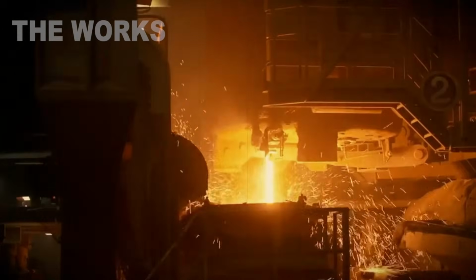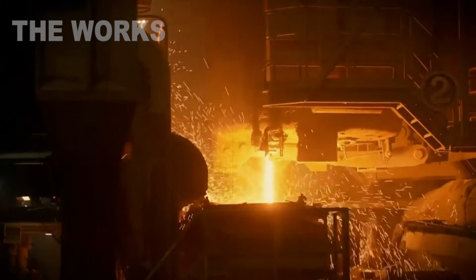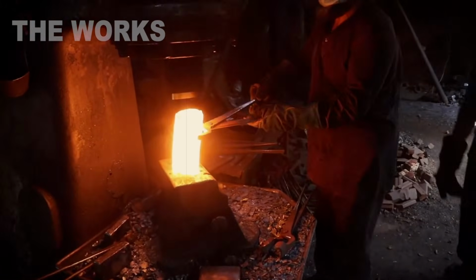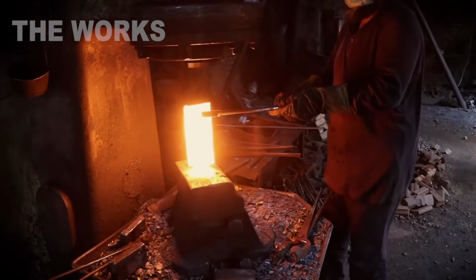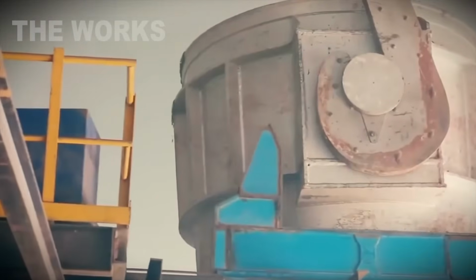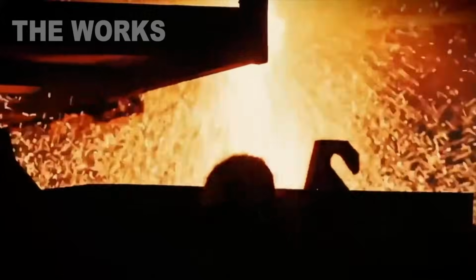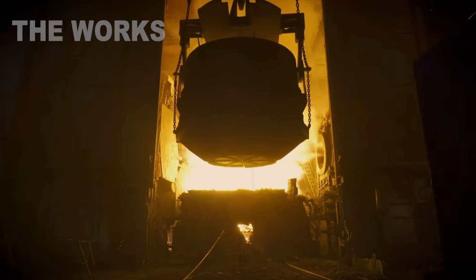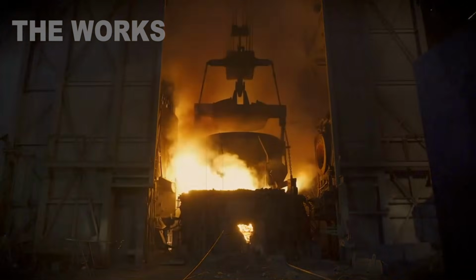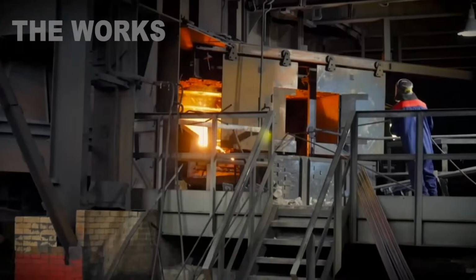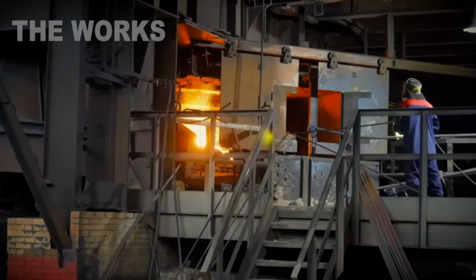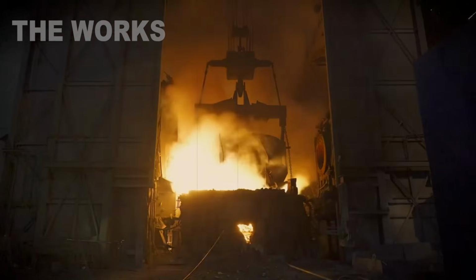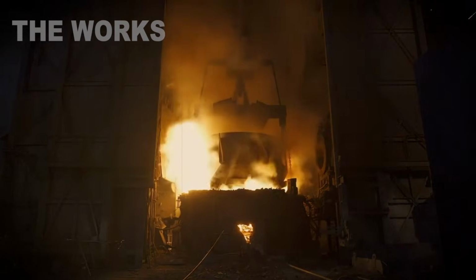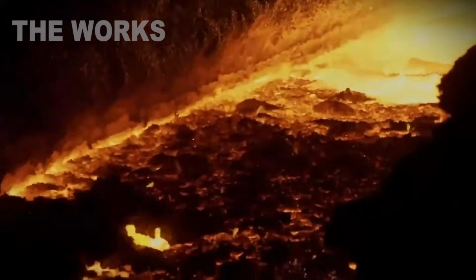Pouring. The mold heats up to 1,800 degrees Fahrenheit. A hot mold means less thermal shock during the pour. A crane brings the steel ladle into position. The steel's at 2,650 degrees. It glows bright orange. They pour fast but carefully. Pour rate is 4 pounds per second. Air bubbles will kill the part. Metal fills the mold from bottom to top, pushes air out through the top.